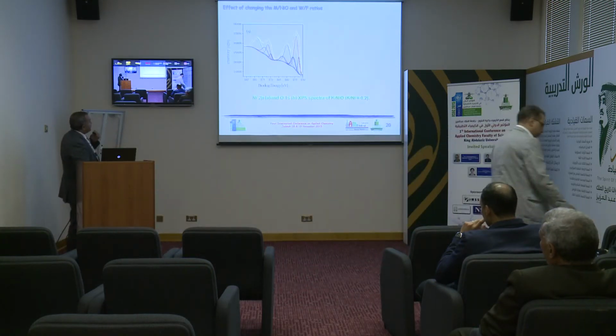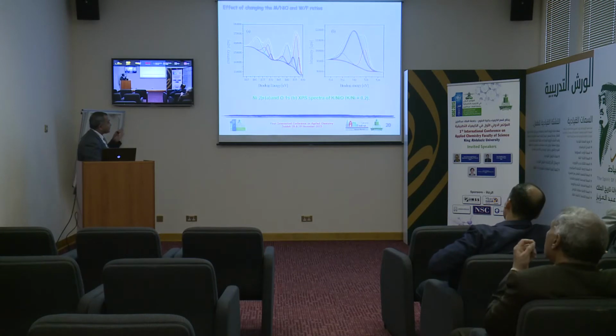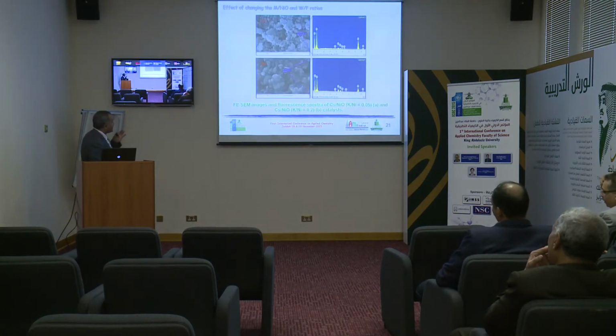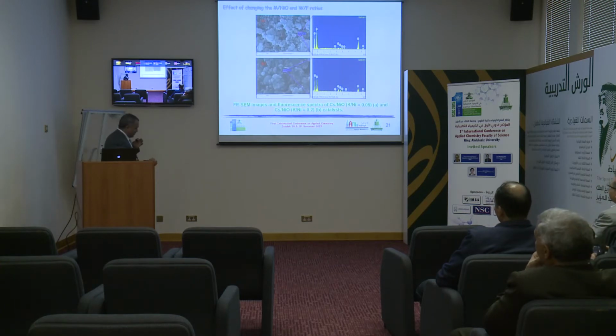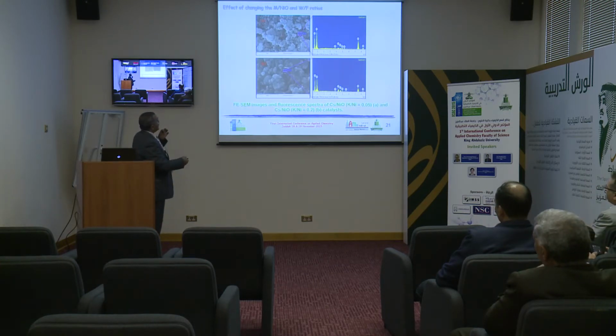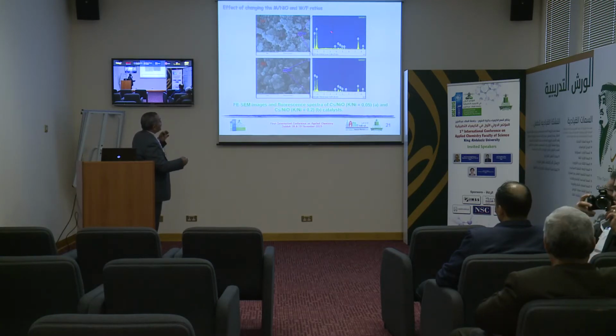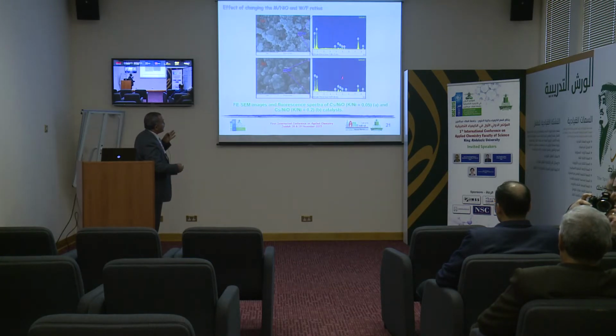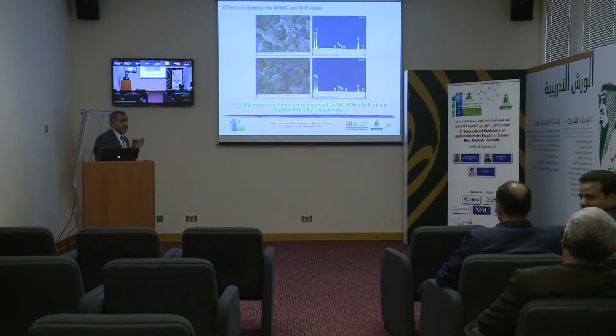Also, going to the XPS data, it's the same. This means we have the same phenomenon, the same active sites. Also we did some SEM analysis and EDX, which showed that we have only nickel, oxygen, and cesium here. I mean the concentration is almost the same among the catalysts.